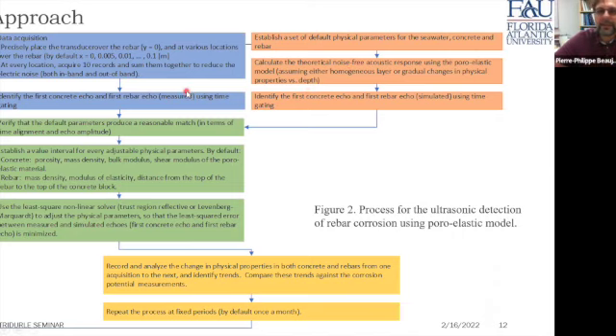Now, after that, both in the measurement and the model, we identify the first concrete echo and the first rebar echo using time gating. Knowing the position of the surface of the block and the position of the rebar, we can have a fairly good idea of where the echoes should be located by having, at least, a good approximation of the speed of sound in the water, in the concrete, and in the rebar.